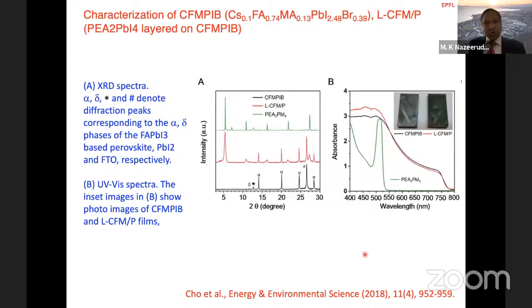Here is the data shown. So we are taking two configurations. One, pure perovskite with cesium, formamidinium, methylammonium, lead iodide, bromide perovskite. This is a normal configuration. It acts like a reference sample. And now we deposited on this sample a layered perovskite. That's a two-dimensional perovskite. So the UV visible spectral data are shown here on the right side. The green line is a pure two-dimensional perovskite involving phenylethylamine as a cation. As you can see, it's a very narrow absorption. A very small portion of the visible light is being absorbed. The black line is a pure three-dimensional perovskite. Now, if we deposit the two-dimensional perovskite on the top of three-dimensional perovskite, the spectral properties are shown.